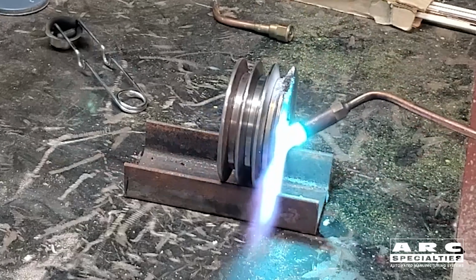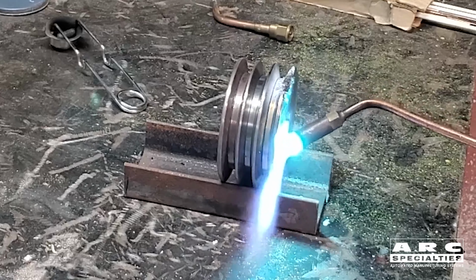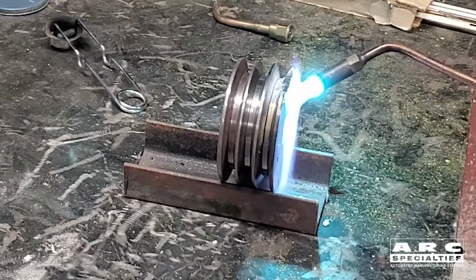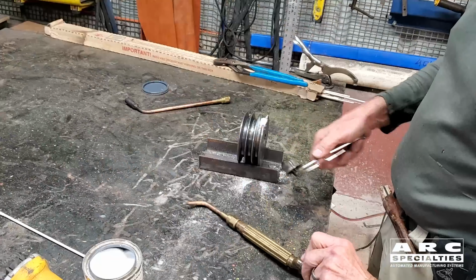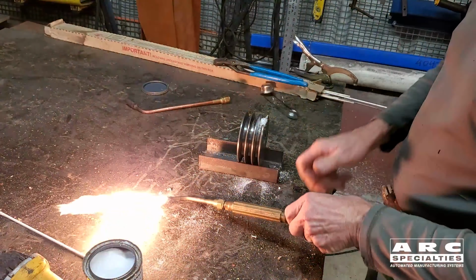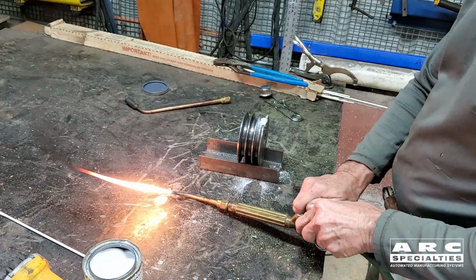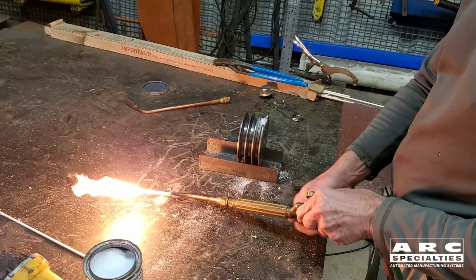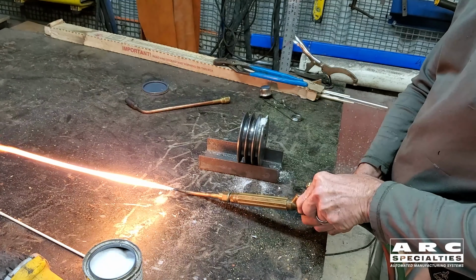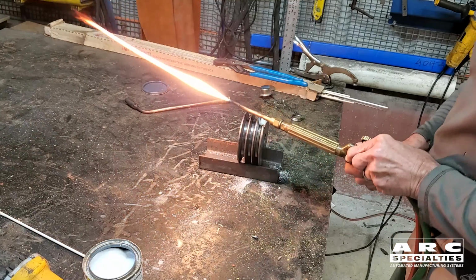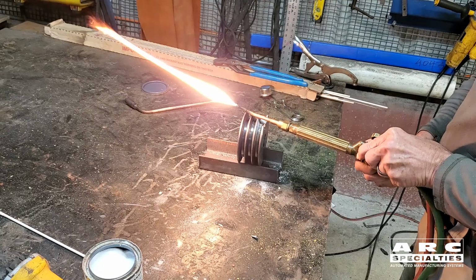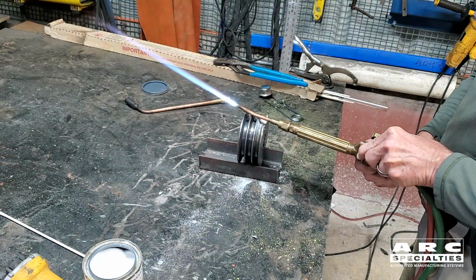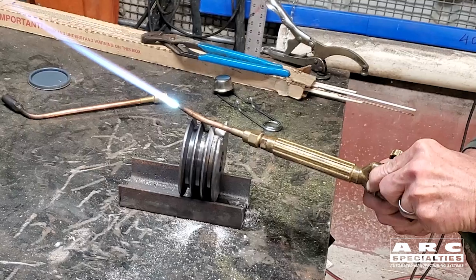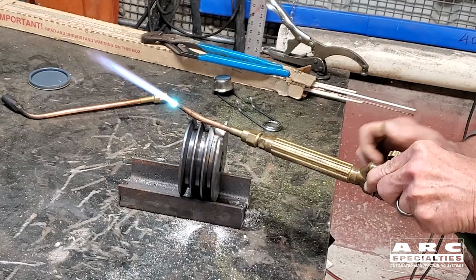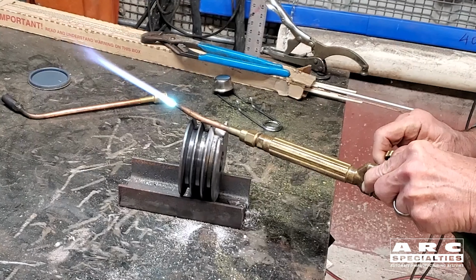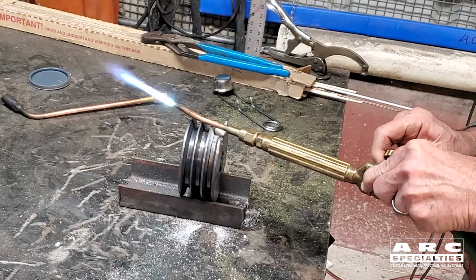The acetylene-oxygen ratio on the rosebud torch isn't critical, but it is on the brazing torch. The proper technique is to open the acetylene valve first, use a striker to ignite the torch, and then add oxygen. What you're looking for is a slightly carburizing or slightly rich flame. This ensures that you don't have an oxidizing flame, which would be detrimental to the part itself. It's impossible to tell if you have too much oxygen. You can only tell if you have too much acetylene. And the way you do that is there's a cone in the center with a slight feather. If there's a slight feather, that's excess acetylene, and that's what we're looking for.